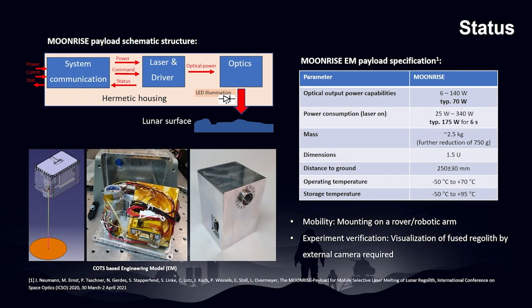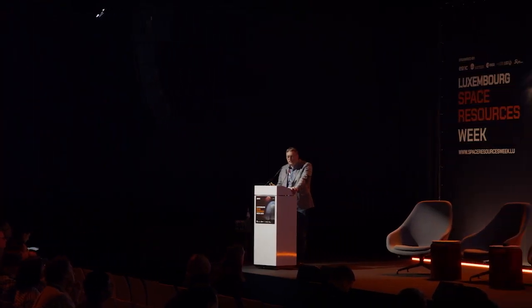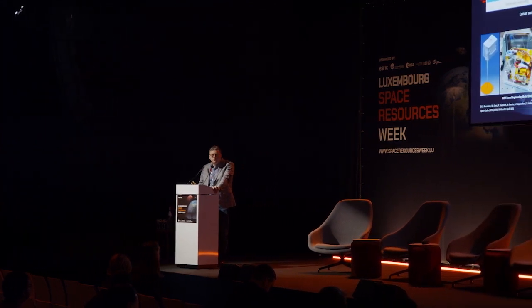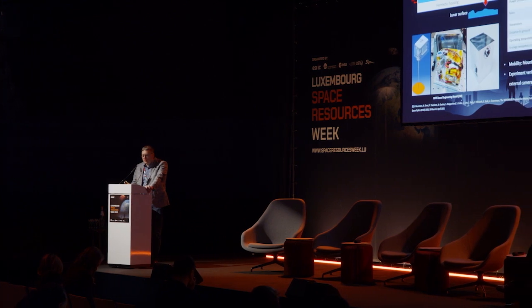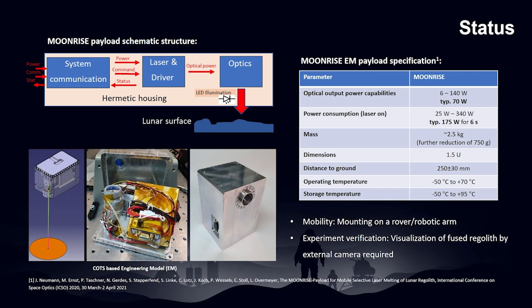So to give you an overview of what the payload looks like, here you see a picture of the actual development status. The payload itself is quite small and lightweight. We focused on minimizing the weight and the complexity of the system. We have a mass of, at the moment, 2.5 kilograms, but we will be below 2 kilograms for the flight hardware. The dimensions are 1.5 U, so CubeSat size, 15 centimeters by 10 centimeters by 10 centimeters. And for the laser, we have an optical output power of 6 to 140 watts, so a broad range of processing parameters we can just adjust by the energy input. And the overall power consumption of this module is 25 watts to 340 watts.